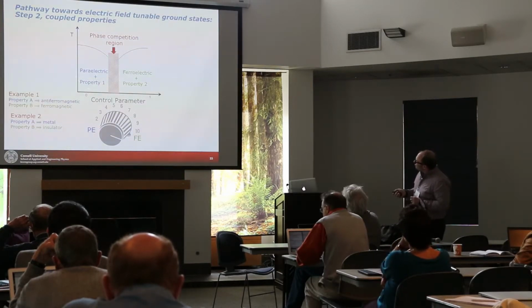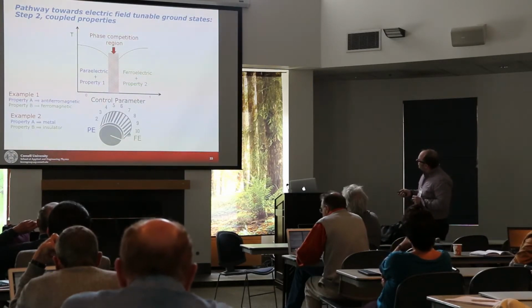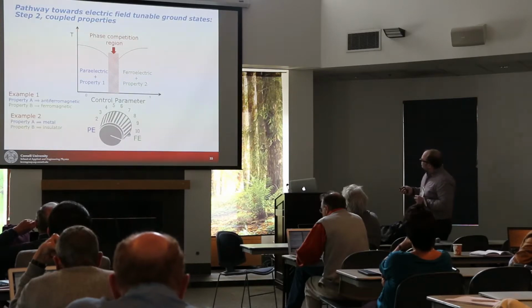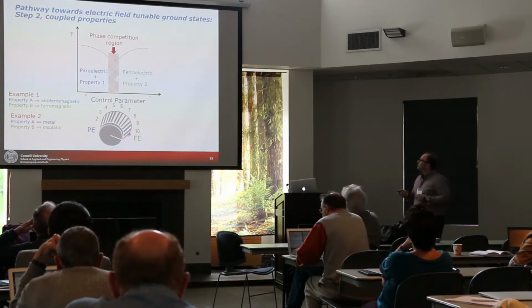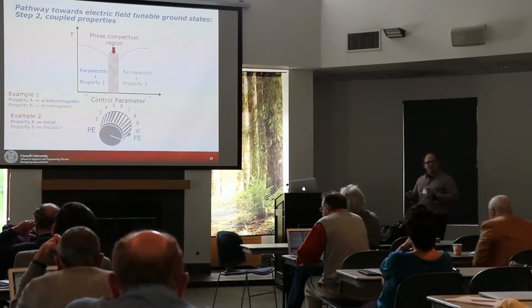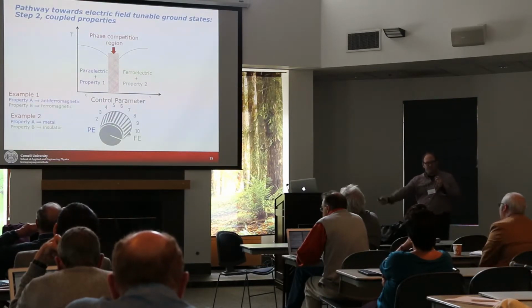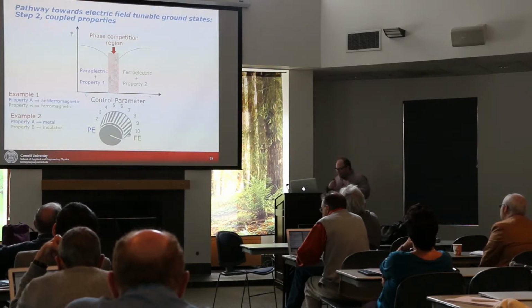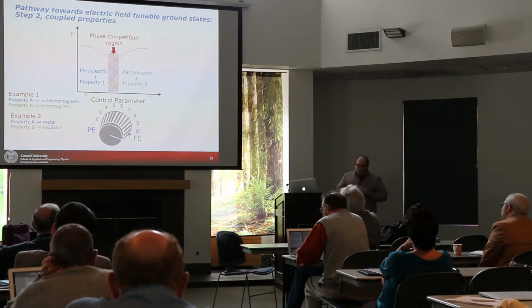Imagine a paraelectric metal and coming up with a way of tuning to a phase that's ferroelectric. In other words, it has to be insulating. So now you're coupling a paraelectric metallic phase to a ferroelectric insulating phase. You couple the metal-insulator transition to a system that has a polarization and one that doesn't. You're coupling all of these degrees of freedom. There's a chance, and it could be a way of controlling that metal-insulator transition.